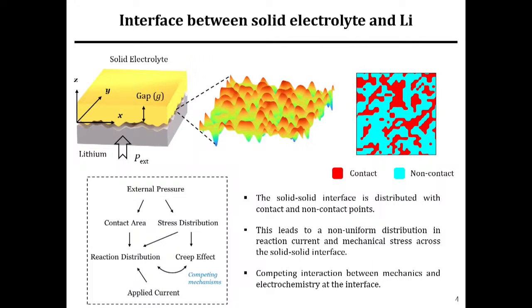In principle, the solid electrolyte or the lithium metal, both of them are not atomically flat. There is an intrinsic roughness associated with their surface profiles, and this requires the application of external pressure in these systems to have good electrochemical contact.